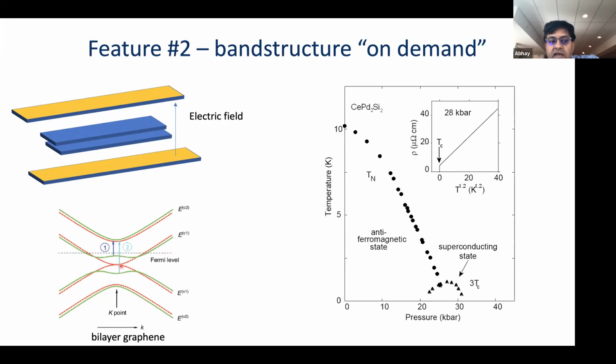So bilayer graphene is a semi-metal, so the band structure looks like this red scenario where you have a conduction and valence band that come and touch at a point. And as soon as you apply this electric field, it opens up a band gap, and so you convert it from a semi-metal to an insulator. And this is another nice degree of freedom with which you can tune the band structure without actually having to make another sample.